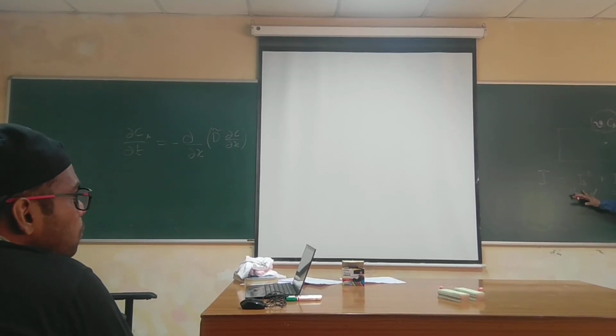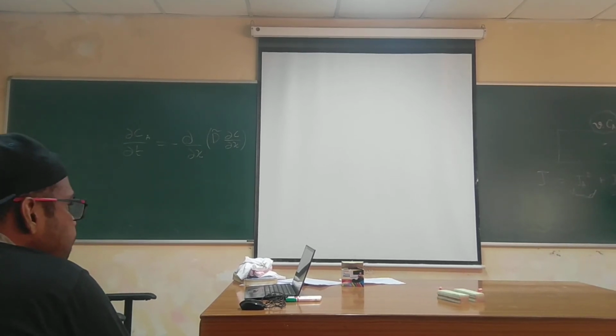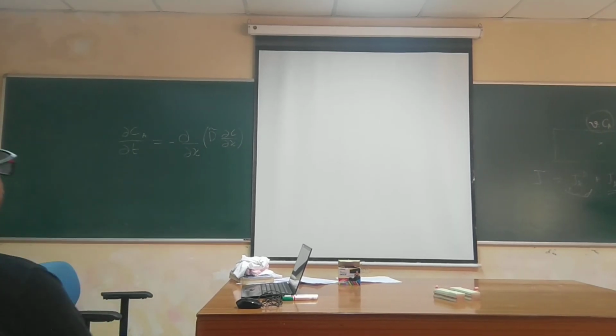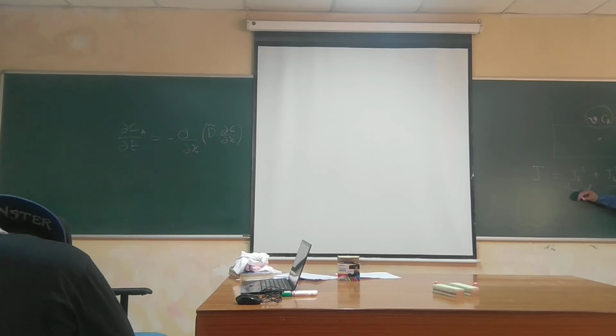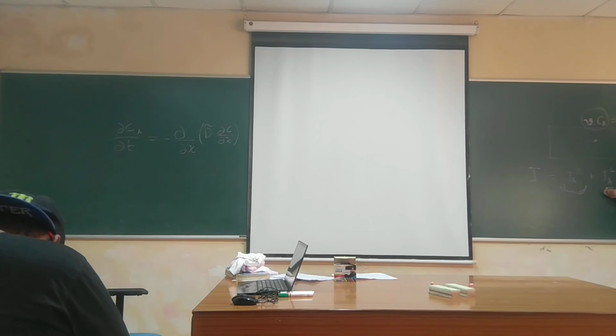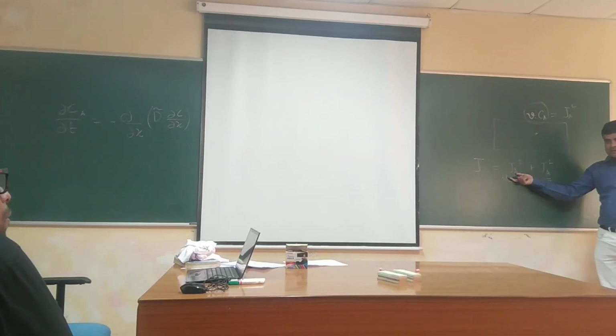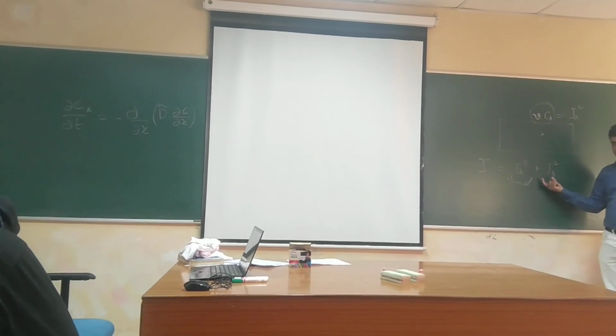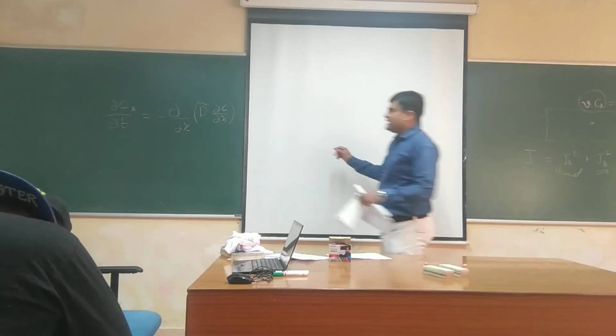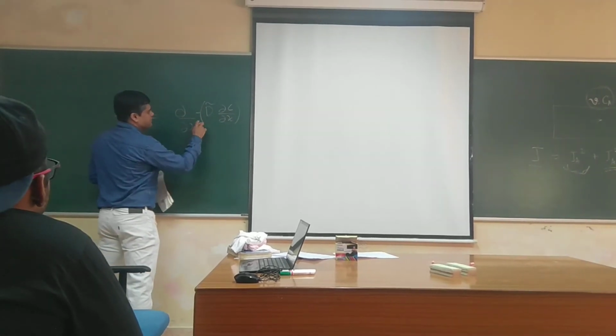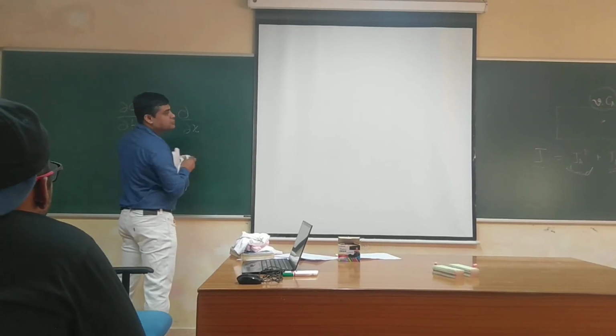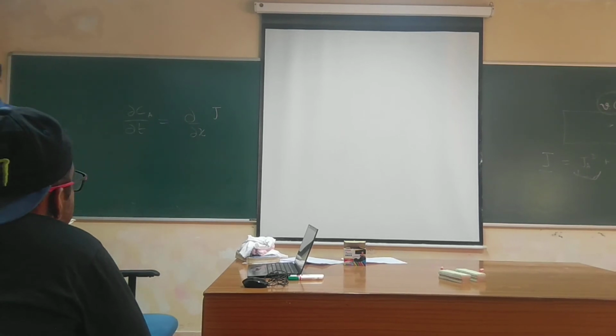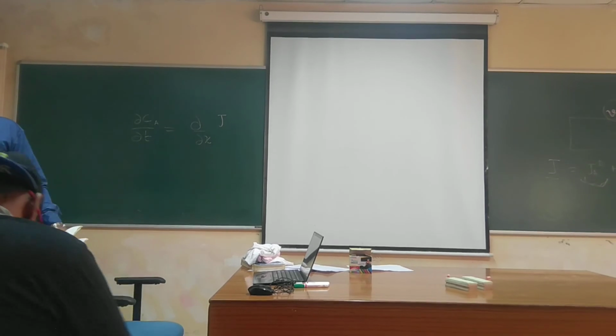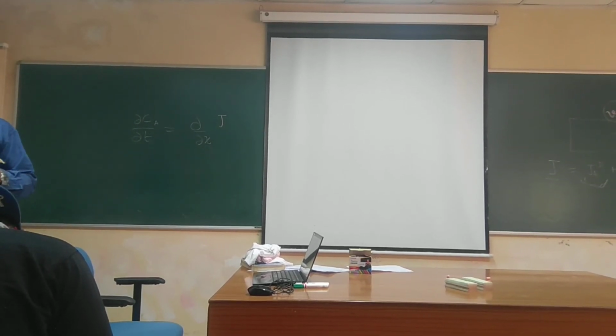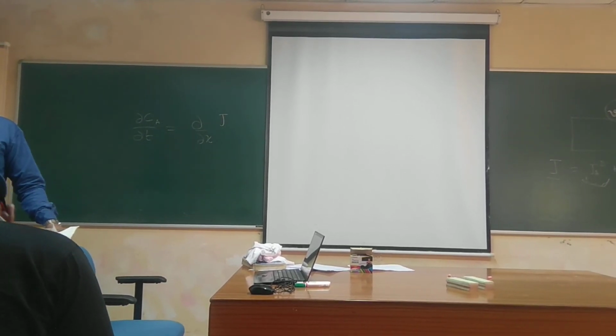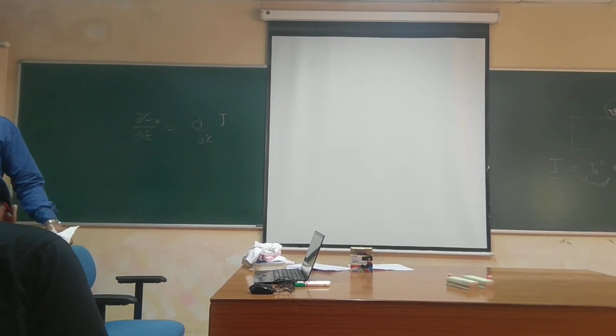Intrinsic flux. Under the chemical potential gradient, that is the diffusive, intrinsic flux. And this is because of the lattice plane movement from outside. So whatever intrinsic flux you get sitting on the lattice, and from outside, if you have to see the total flux. Now this minus d dc dx, if I take the minus inside, is the flux. So that flux is actually the total flux. The d tilde is characteristic of the total flux. You are looking from outside, d tilde is a measure of how quickly the intermixing happens. So it is from outside, the total flux of any component A.